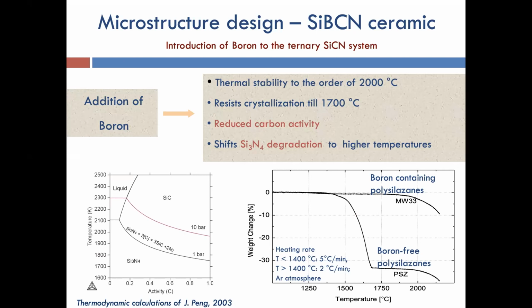So crystallization is resisted till 1700 degrees Celsius. And because of the addition of boron, I will also show you that the carbon activity is reduced to a large extent, which helps delay the degradation of silicon nitride to much higher temperatures.